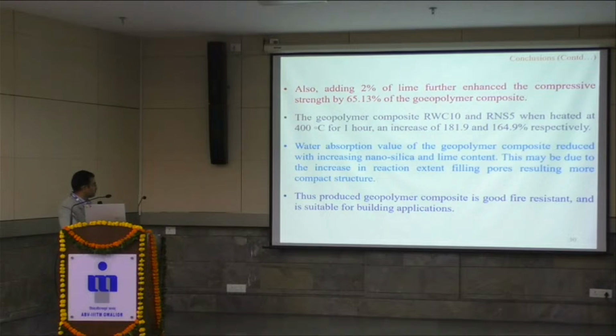65%. And the geopolymer composites RWC10 and RNS5, when heated at 400 degrees centigrade for 1 hour, were found to increase in strength by about 181.9 and 164.9% respectively. The water absorption value of the geopolymer composite reduces with the addition of nanosilica, and thus the produced geopolymer composite is a good fire resistant and is suitable for building applications.